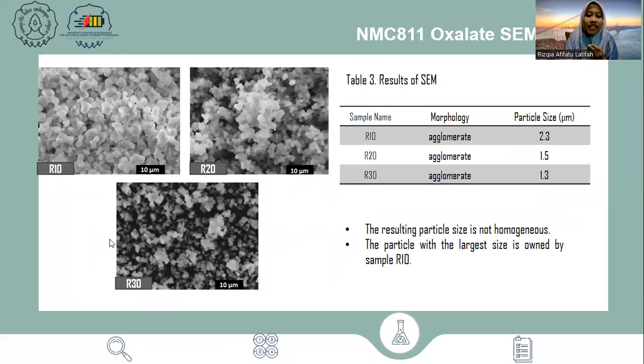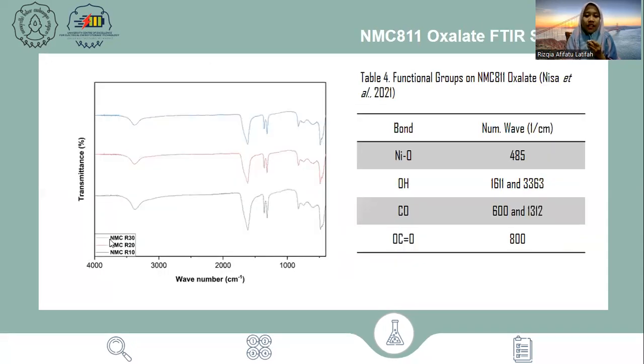The next is the result of characterization using scanning electron microscope. The resulting particles have agglomerate shapes with sizes that are not homogeneous. The particle with the largest size is owned by the sample with the variation of 10 g/L. And then the nickel manganese cobalt material was also tested using Fourier transform infrared spectroscopy, and the following is the resulting spectrum.